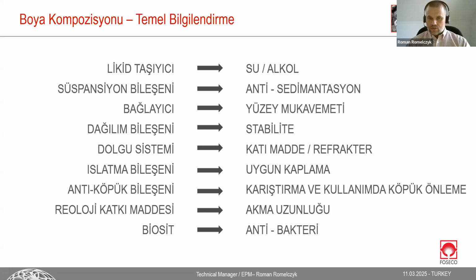When we talk about alcohol-based coating, of course, this kind of wetting agent does not exist, because alcohol itself has a very small, or depending on the literature very big, wetting angle, so there is no problem with it. Anti-foaming agent, for both alcohol and water. During mixing, usage, circulation, dilution, and all these manipulations, we sometimes mix very turbulently. This part of the coating prevents foam and bubbles from being trapped in the coating itself.